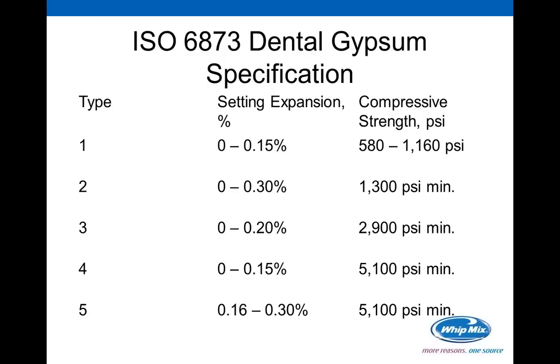The interesting thing to note about dental technicians is that for some reason out there at some point in time, we started believing that compressive strength meant hardness, and it doesn't necessarily mean that. What it does mean for sure, if you change from a type 4 to a type 5 die stone, is that you will get increased expansions. And you need to factor that into your thinking and into your planning for what's going to happen in your dental laboratory.